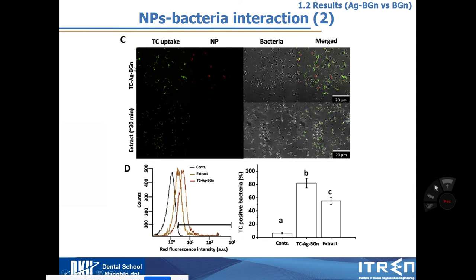So actually this TC-Ag-BGn was co-cultured with bacteria for 30 minutes. As a control group, I independently incubated TC-Ag-BGn in bacteria culture media. And then I collected the extract, and then I used the extract to co-culture with the bacteria for 30 minutes. And then I found that compared to only the released tetracycline from the extract, this direct interaction between nanoparticle and bacteria has higher tetracycline delivery.